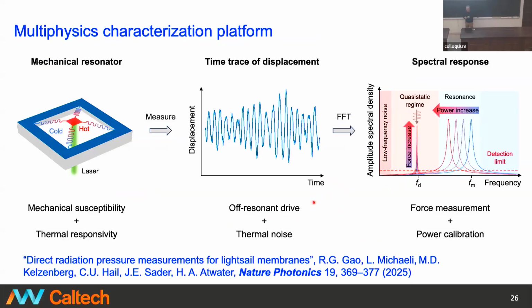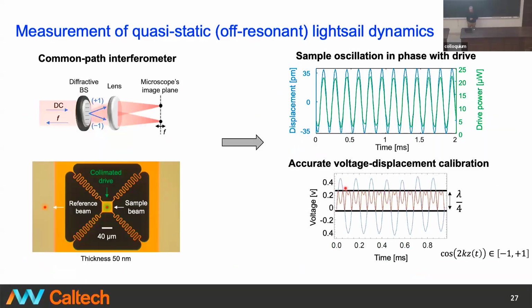To analyze this, we built a characterization platform that includes the oscillator itself, and something that allows us to make very sensitive measurements of displacement, and also to look at the change in the resonant frequency, which is due to linear or nonlinear changes in the materials properties. The resonators themselves look like this. They're analyzed using a structure called a common path interferometer. This is an interferometer that has a reference beam and a probe beam. As any experimentalist knows, everything in the lab vibrates, and we want to make measurements with picometer resolution. The mechanical resolution attributable to this common path interferometer is about 10 picometers.